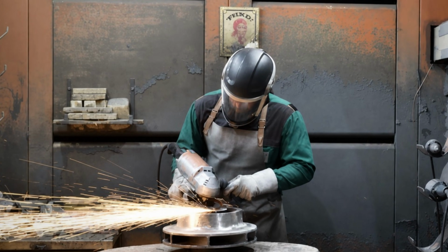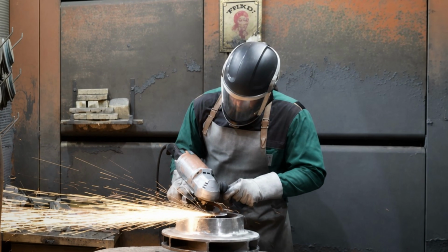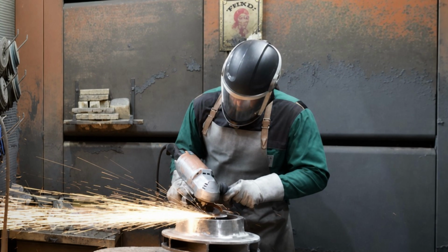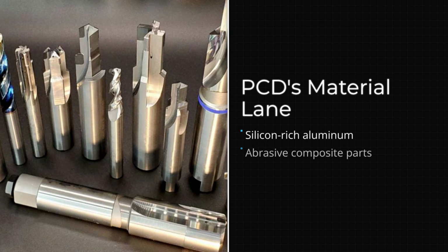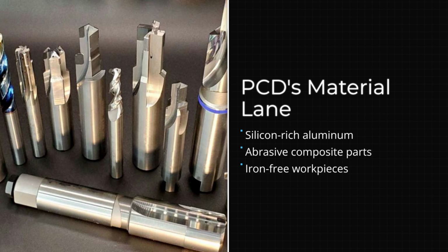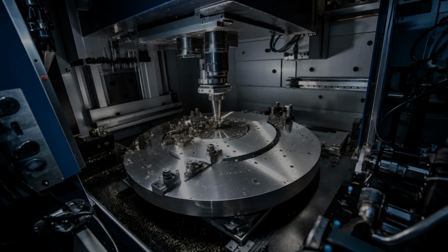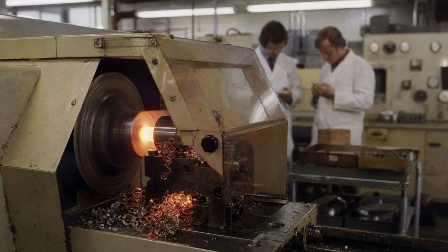Its sibling, polycrystalline diamond, sintered under the trade names Compax and Syndite, owns the other side of the map: high-silicon aluminum, composites, anything abrasive and iron-free, where tool life against carbide can run to 100 times. Point it at steel, and the carbon dissolves into the chip. Every super-hard material has a lane, and the lanes don't overlap.